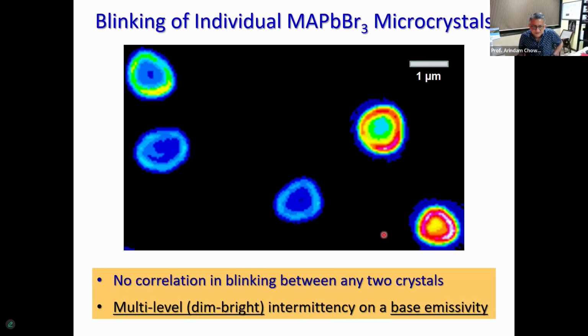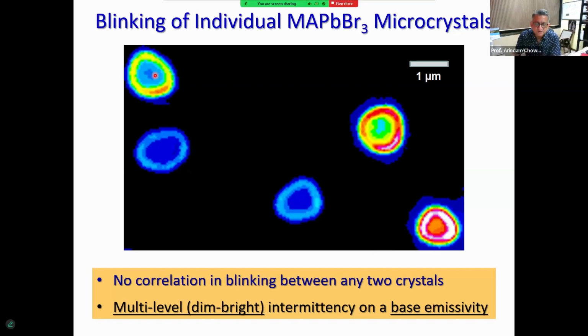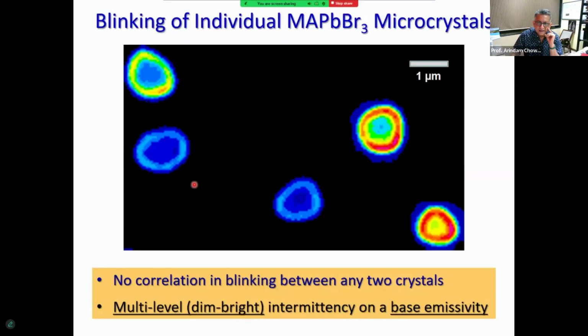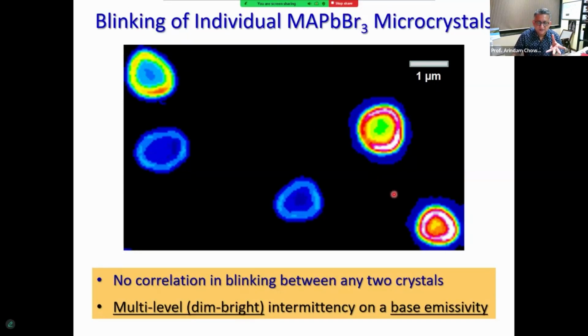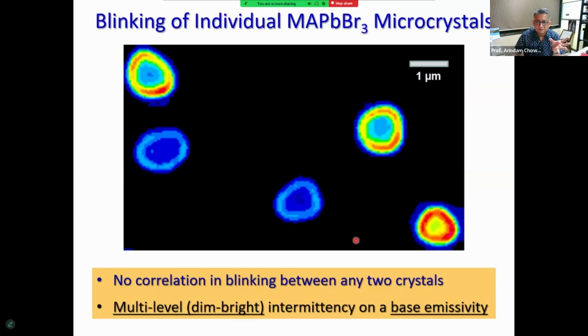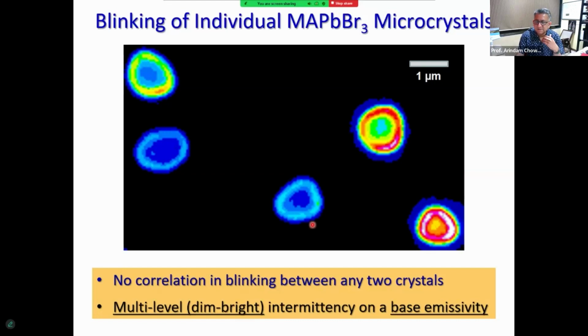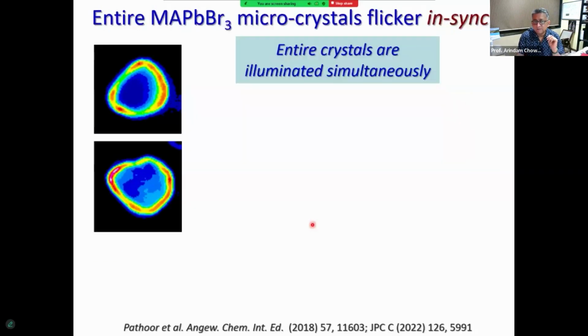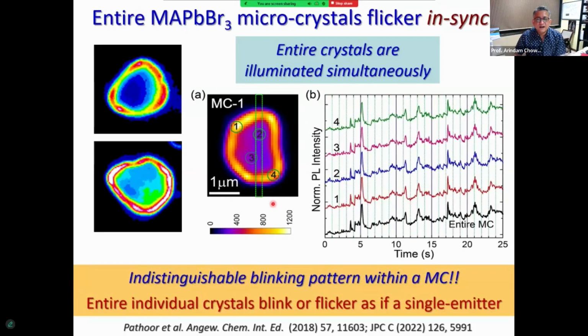And this is an example of what we did see. We started seeing that individual crystals, they are not joined, they are isolated. They are blinking vigorously. This is real-time data that I'm showing you. And not only that, if you notice carefully, they all blink in a different manner. That means this is not an effect of my excitation laser fluctuation or my focus drift or anything. It's a multi-level blinking that is happening. And if you look even more carefully, you would see that entire crystals, which are simultaneously illuminated by our laser light, seem to be undergoing this fluctuation together. This is what I would now call a spatially correlated blinking behavior.